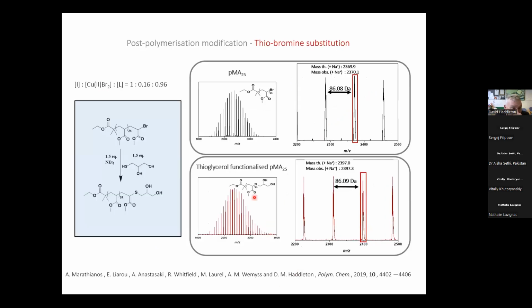Then what we do in flow on this one, we are then functionalizing our polymer as it comes out by reacting with a thiol. And I've just shown you some MALDI. So this is polymethyl acrylate, again, pretty much perfect, no termination. And then when we add in the thiol, in this case, it's thioglycerol, you get a nucleophilic displacement of the bromine, and you get the change in molecular weight. And so you get almost perfect functionalization.